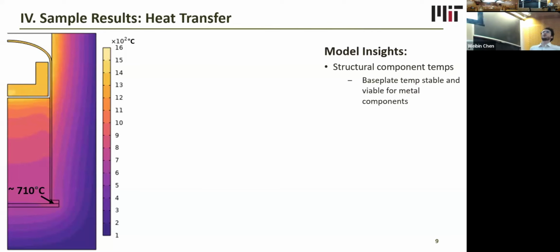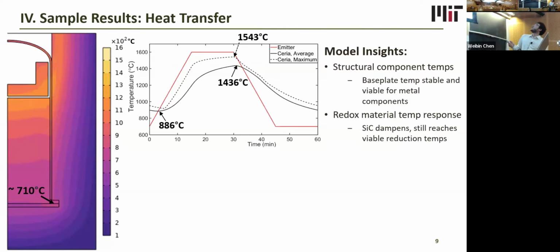We can see in this animation showing the temperature fields throughout the entire cycle that the redox zone is undergoing a significant temperature swing, while the inner insulation is successfully shielding the metal components at the back of the reactor from this high temperature swing and keeping it at a lower, more acceptable temperature that could be used for something like Inconel. We also have here a plot of the time-dependent average ceria temperature in solid black and maximum ceria temperature in dash black lines. And while this design using the opaque absorber emitter does result in some temperature dampening response, it doesn't reach the full temperatures of the emitter, we are attaining viable redox temperatures.